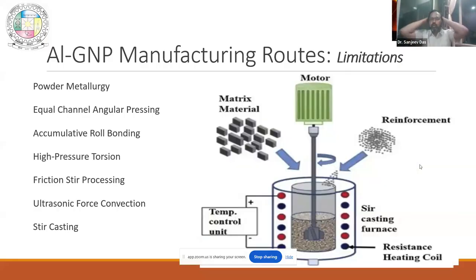So initially I showed you there will be a vortex formation. In that vortex you have to add the particles. Now when there is a vortex formation, anything on the surface goes inside the liquid metal. Suppose you form some dross or slag at the top, or there is air at the top, everything goes inside your liquid metal, so it will be full of porosity, gas bubbles, slag, or whatever unwanted thing was at the top, and finally it is contaminating your melt. And now you are doing casting and whatever ultrasonic treatment, you are not able to get rid of those things which you have added by creating the vortex.